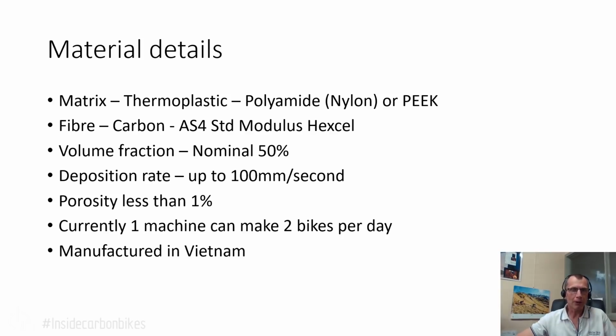In the white paper, they spoke about the fiber volume fraction, and that was a nominal 50%, which is a little bit on the low side. Typically with autoclaved, cured pre-preg, you're approaching 63%, depending on your fabric type. So for laying down bundles of fiber, 50% is probably a little bit low, but obviously that's related to the process that they're using and the deposition rate. So we'll talk about a little bit of that.